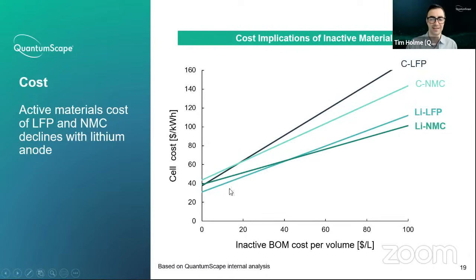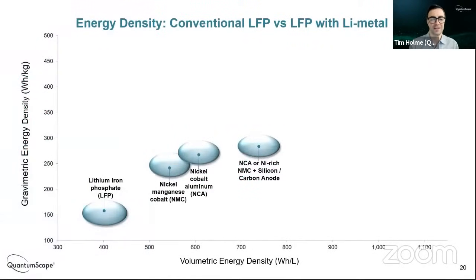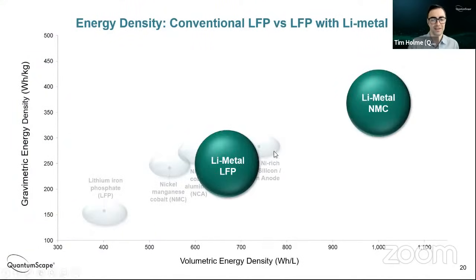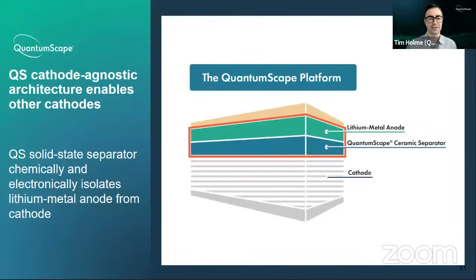So pretty interesting that you can reach a crossover point here, and LFP becomes the lower cost cell. So how does that change the landscape of energy density that we looked at before? If you remove the hosted anode and go to a lithium metal anode, you can, as we've been describing, go to higher energy densities. And one really interesting takeaway from this chart here is you can take LFP into the range of today's commercial NMC type cells by replacing the hosted anode with the lithium metal. And of course, the NMC type cell will still offer the higher energy density, so it would be great for longer range cars. So the QuantumScape platform then is relatively agnostic.